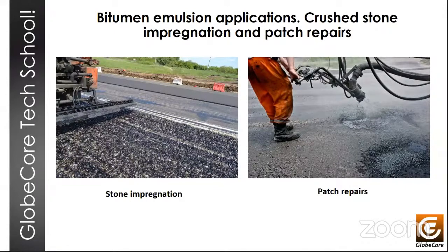And there is patch repairs. The use of bitumen emulsions greatly simplifies the repair process. It allows work to start in early spring and end in late autumn, especially in moderate climates like what we have. It can be used at air temperatures as low as 5 degrees Celsius.